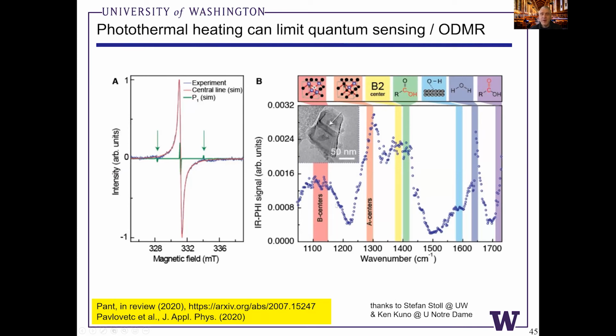This is photothermal heterodyne imaging spectroscopy, where effectively you're using nonlinear difference frequency generation to produce very high spatial precision, very localized difference frequency photons in the infrared region. You have a secondary probe laser that probes the thermal deflection of that local sample after absorption of this infrared range. And we can see what we could potentially identify as B centers in these HPHT materials.